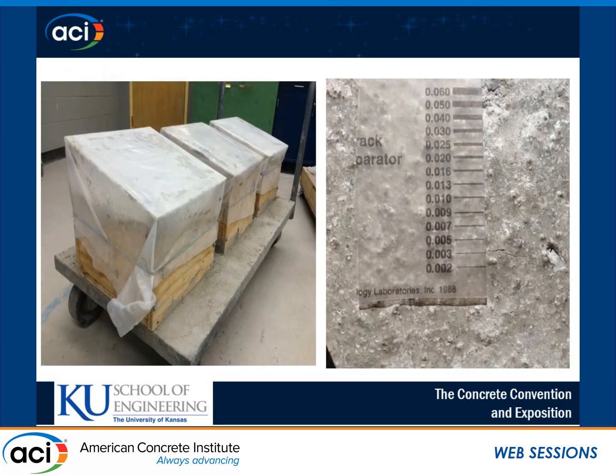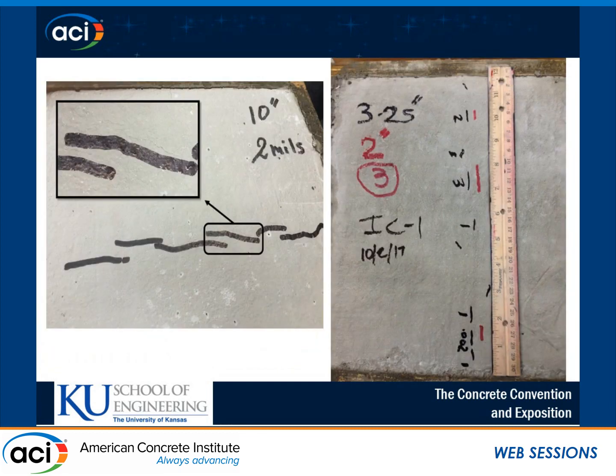And after we place that sloped plexiglass on top of the forms, we seal those with a plastic sheet and seal that off with a rubber band. So not very complicated. And after 24 hours, we measure both the length and width of each resultant crack. So here's the finished product. It's also important to note that the only cracks that we're actually counting are the ones that develop directly over the surface of that piece of rebar.